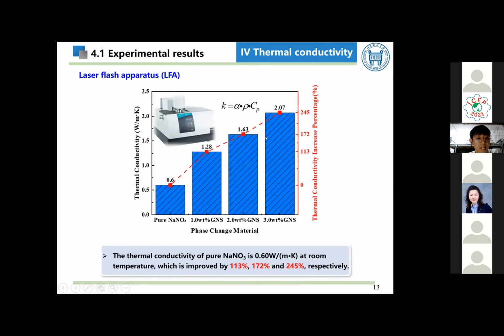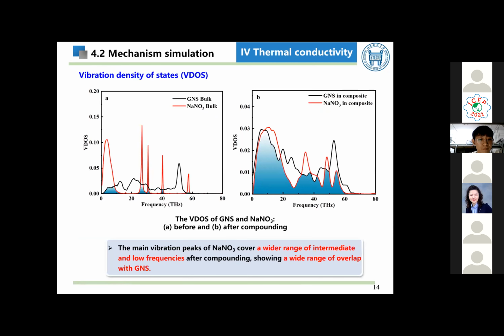As for the thermal conductivity, the thermal diffusivity of the composite was measured firstly by laser flash at room temperature. Then the thermal conductivity was calculated by following equation. Apparently, the thermal conductivity of the composites was significantly improved, an increase of 245% with 3% doping ratio, achieving a breakthrough in the order of magnitude. Here, we try to explain